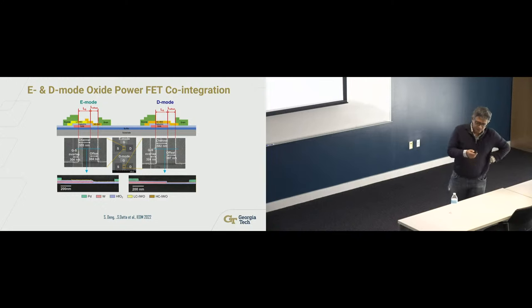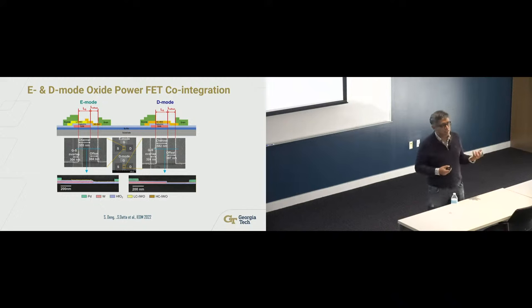We use tungsten doped indium oxide is our chosen material. It can go down at low temperature, which doesn't bother the front end of the very sensitive FEOL transistors. And we can make this enhancement mode and depletion mode. Basically, the idea is to make a switched capacitor DC-DC voltage converter.